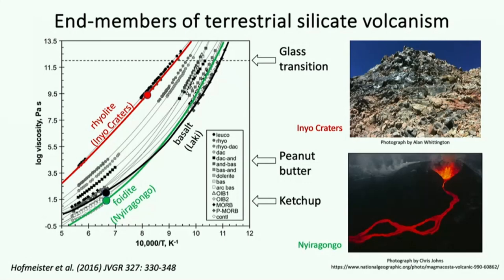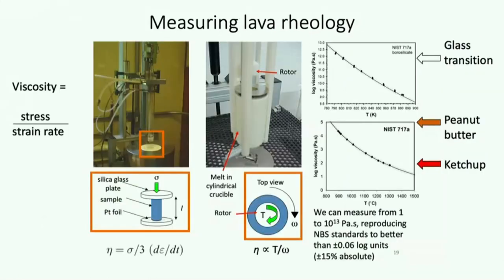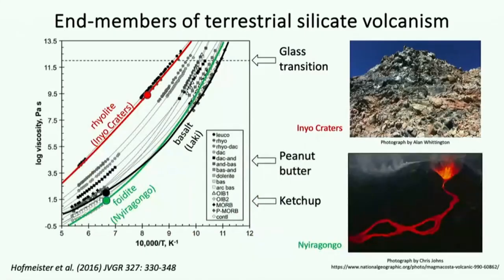So it's not that the isotopes aren't important. They are, and you do need to measure them that precisely. I guess the good thing is, if we can measure things to plus or minus 10%, that is 0.04 log units, that's like the gold standard. The certified reference materials, the curves there are the certified values and the points are our measurements on the certified material. Those certified reference values actually have uncertainties that are close to plus or minus half a log unit. People don't normally talk about that, but anyway.